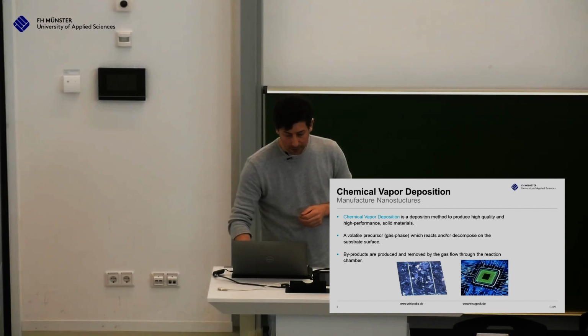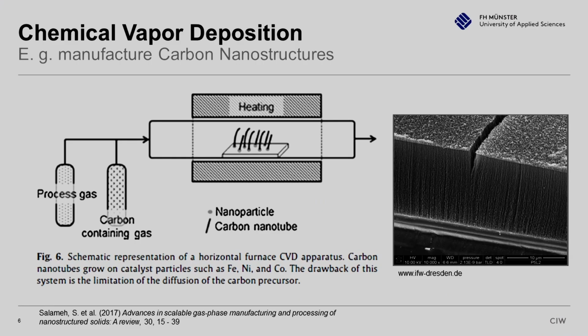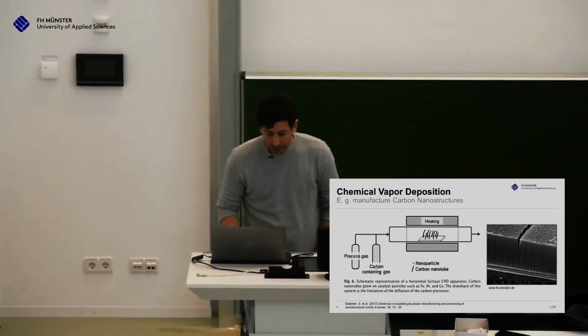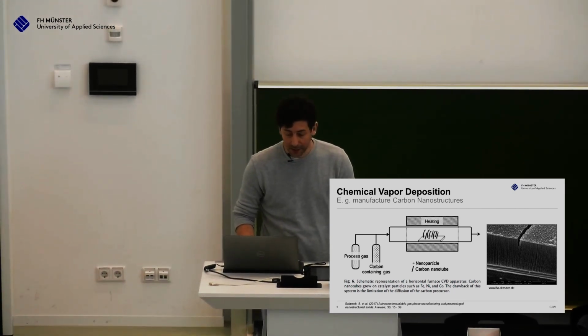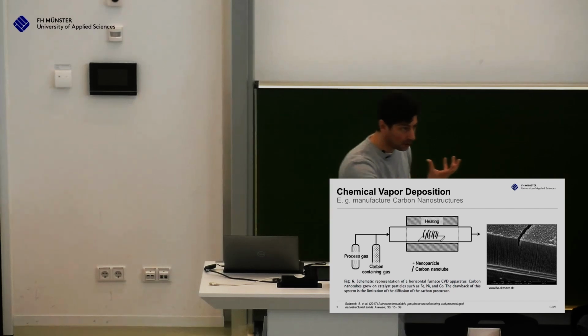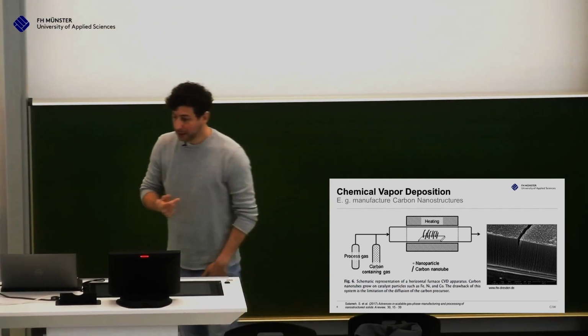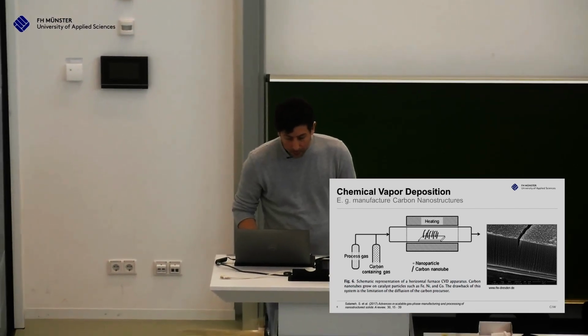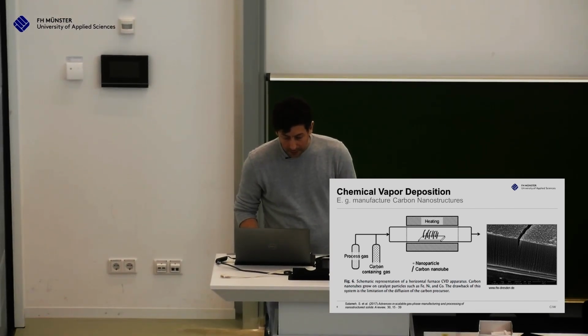And another example, and this is what you see here, is chemical vapor deposition to create carbon nanotubes. So you have a process gas and a carbon-containing gas. The carbon-containing gas is the source you need to grow your nanotubes, and the process gas is basically to carry this carbon gas, right? So it goes into the chamber, and in the chamber you need nuclei for your nanotubes. Here you see heating around the chamber, so you need a hot environment. This means we have hot wall CVD here. And once the gas goes in, the reaction starts, and the catalyst particles, as you see here, iron or nickel, and then the nanotubes are growing.